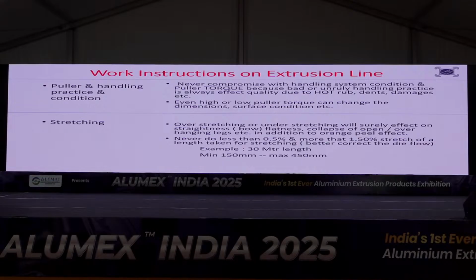See here, this is a very important area. Now, how will you define 1.5% stretching? It's very easy. You have a 30 meter length of extrusion. Just place it, hold it with your head and tail stock, look at your stretcher pressure gauge, and from there you start measuring. If you want to do 1%, 300 millimeter. Allow your headstock to travel 300 millimeter. And if you can afford, you can put an encoder and a pressure sensor. It will be very easy. Why depend on a very ultra skilled person who knows stretching, and when he is on leave, no one knows? That is why this has happened. Not like that.